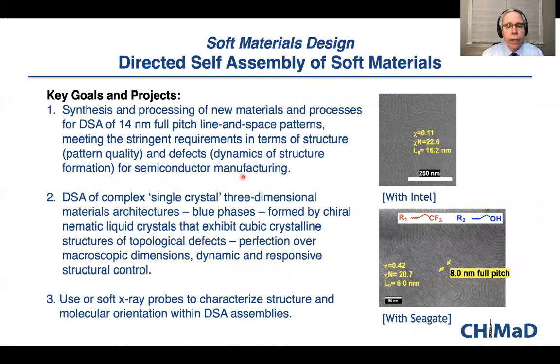And so in the past year, they've achieved a 14 nanometer pitch with very low defect quality, but they're also pushing it to still smaller levels. This is an 8 nanometer pitch working with Seagate, for example. And they're also looking at three-dimensional self-organization processes using blue phases and three-dimensional architectures. As I said, soft X-ray probes or X-ray characterization is an important part of this use case.